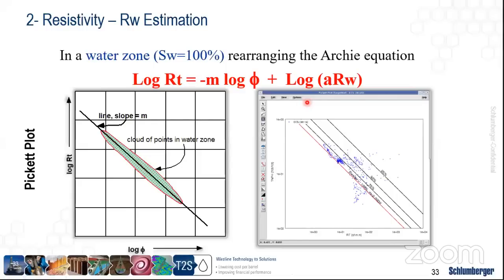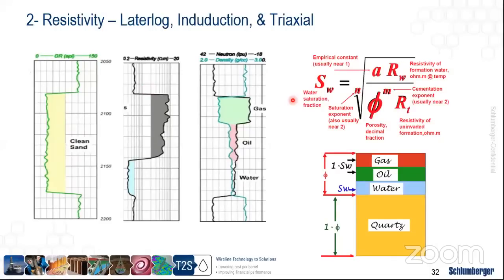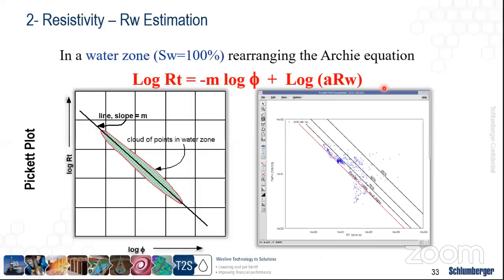we go to the water zone and then use Archie's equation by taking log of both sides. So taking log of this side and log of the other side, we can derive this basic equation by assuming SW is equal to 1. So it's log RT is equal to minus m log phi plus log A RW. So if you have a closer look at this equation, it represents what we call the equation of a straight line, where y is equal to mx plus c, where m represents the slope and x is the independent measurement, and c is the intercept.